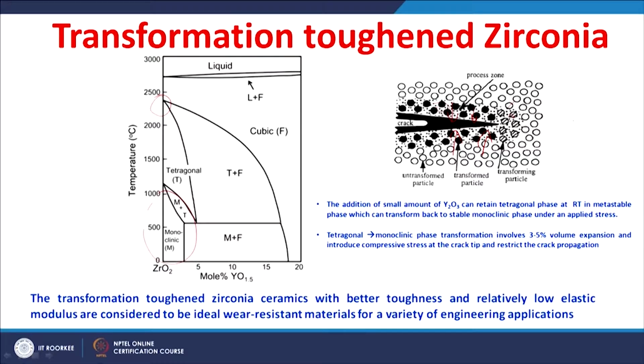So, the crack will not propagate easily, and you get a fracture toughness improvement. This transformation toughens the zirconia. These transformation toughened zirconia ceramics with higher fracture toughness and relatively low elastic modulus are considered to be candidate materials for several wear resistant applications. So, today we consider these yttria stabilized tetragonal zirconia polycrystalline ceramics for understanding their wear behavior.